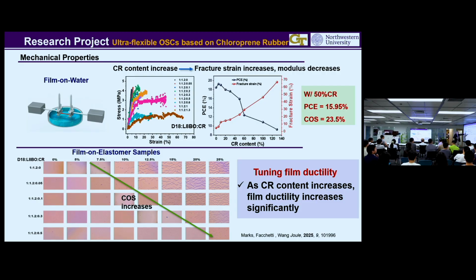And what you can see here, this is stress versus strain. When you put stress on it, when does it break? And so these curves where it goes up and then stops means that it's broke at this point. Look at this one now. So you can maintain a lot of the power conversion efficiency, a lot of the electronic properties, and get this stretchability.